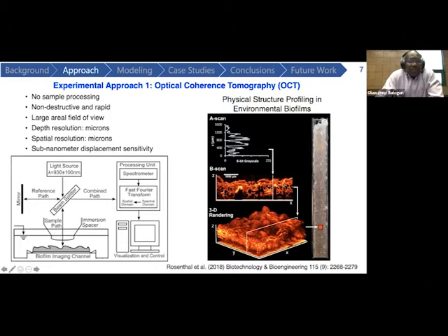And the heat map you see is a measure of the light scattering intensity. The dark spots are regions in which you have water-filled voids or channels, and the hot spots represent the actual polymeric substance, the extracellular polymeric substance, or the biomass, if you will. From images like this, both in 2D and 3D, one can analyze them and obtain areal porosity as a function of depth. This would help us characterize the volume fraction of water within this biofilm. So that's one attribute that one can get from this.